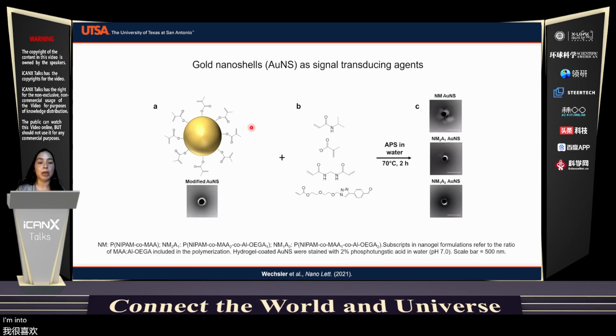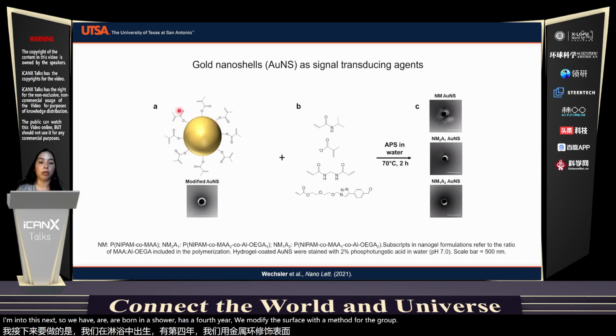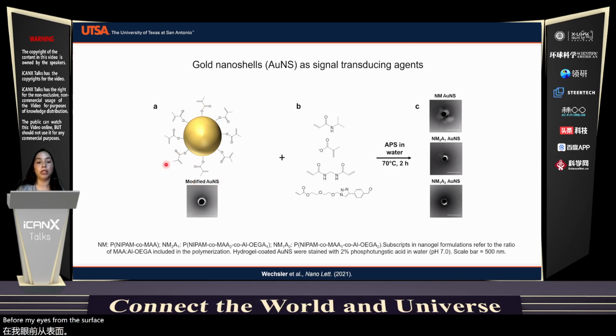into this mix. So we have our gold nanoshell as a core here. We modify the surface with a methacrylate group to serve as an anchor from which our polymer can then be polymerized. So we use that same polymerization scheme in the slide that I showed previously that polymerizes from the methacrylate group on the surface. So here's our modified gold nanoshell. We use the same monomers as described previously, and we get these kind of flower-like structures on the surface.